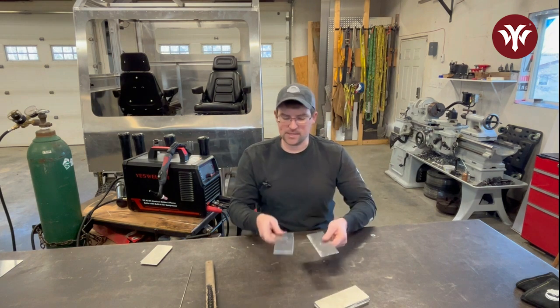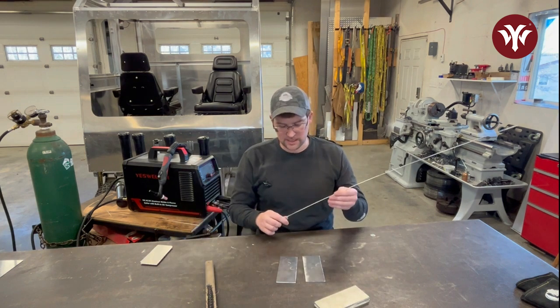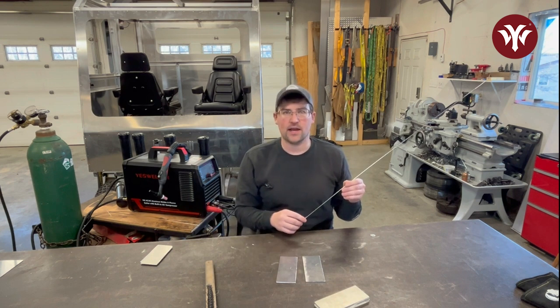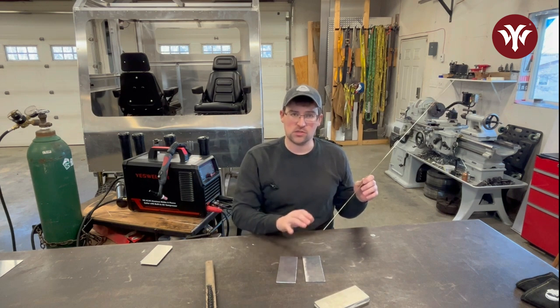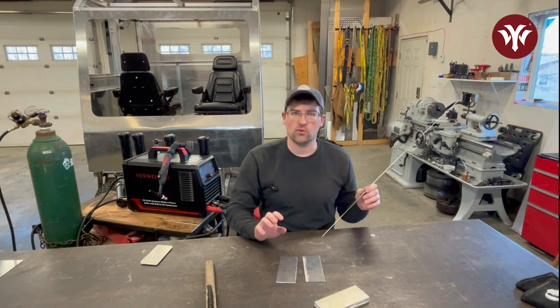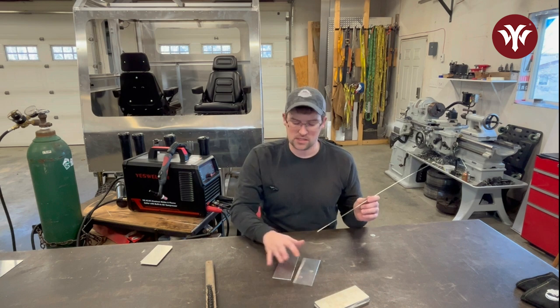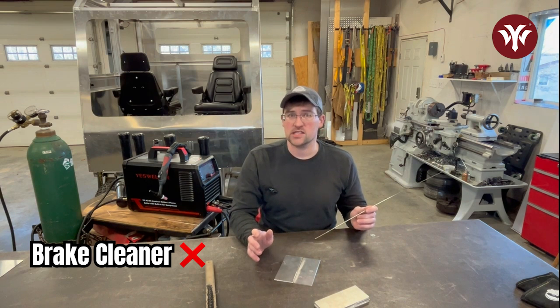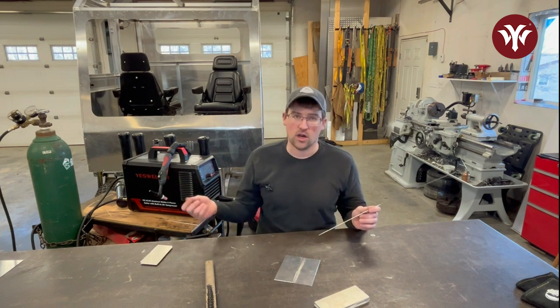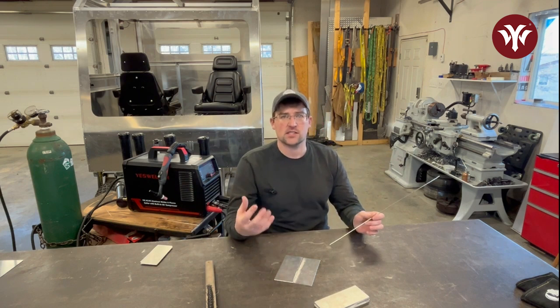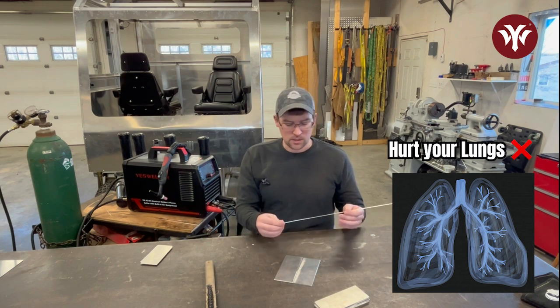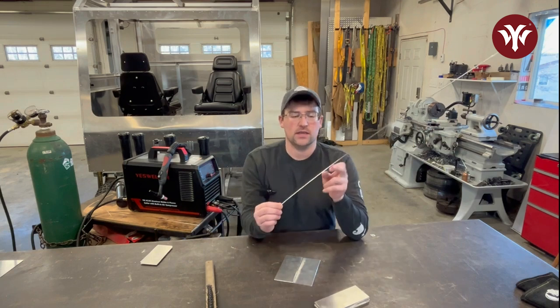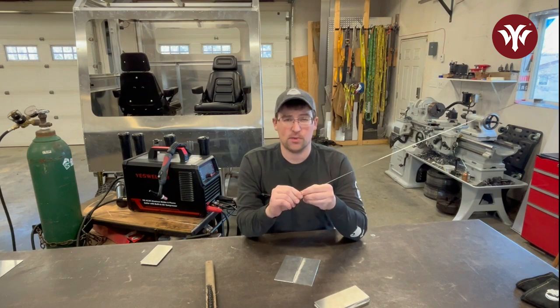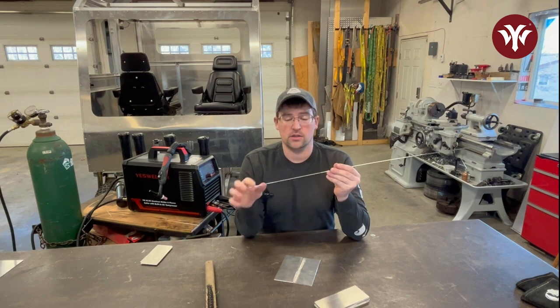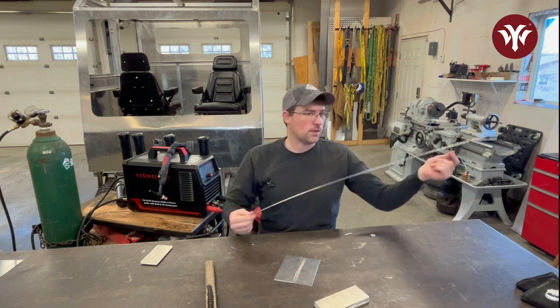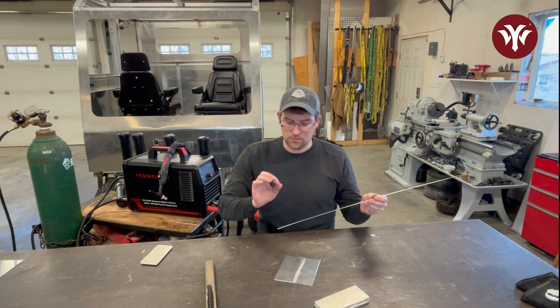All right, since we're talking about base metal and we've talked a little about filler rods, as I said before, when you're wiping your parts down with acetone, which is a safe solvent, it evaporates off really quickly with no residues and it's not going to harm you through welding processes. You're not supposed to use brake cleaner or things like that. When exposed to the arc, if it hasn't fully evaporated, it can create some very toxic gases which can really hurt your lungs. The other thing is wipe your filler rods down with acetone because they get oxide on them too. You can even take a Scotch-Brite pad if you feel you have some heavy oxide on your filler rods and just run them through, wipe them with acetone, and it's just going to help you achieve that weld you're looking for.